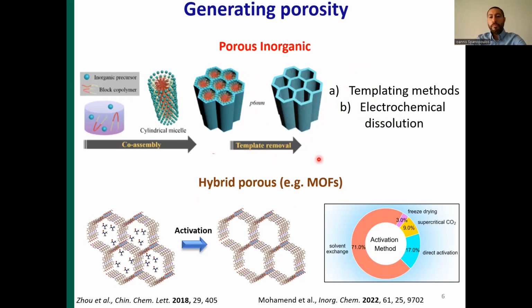On the other hand, in the case of porous hybrid materials like metal organic frameworks or coordination polymers, these compounds form 3D and 2D networks, where in the pores that are formed usually reside solvent molecules. And these solvent molecules, because they are not countercations, they do not charge balance the structure, can be removed by using different activation protocols. And upon their removal, a porous network, a porous framework, a porous material can be acquired.